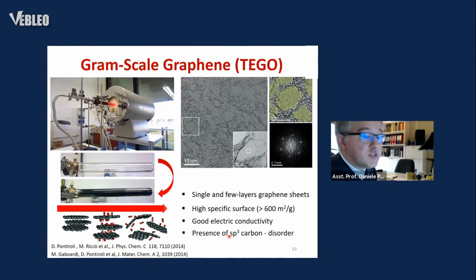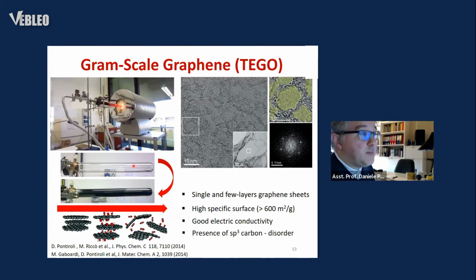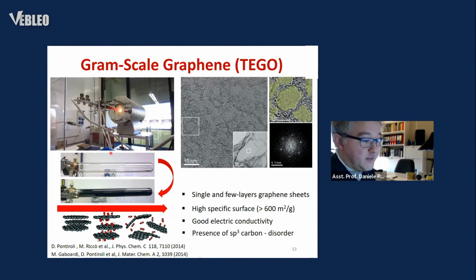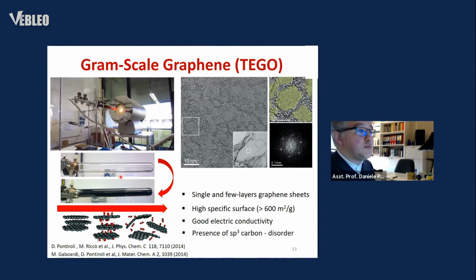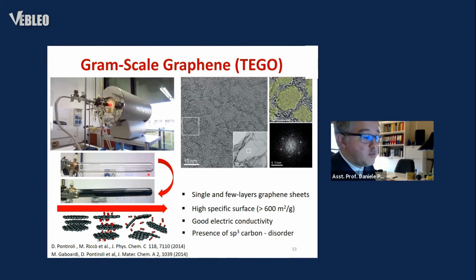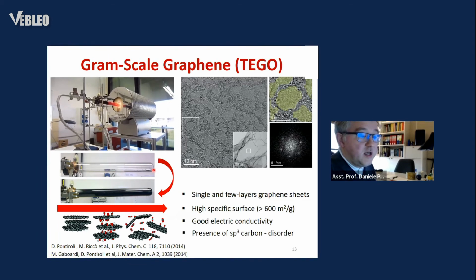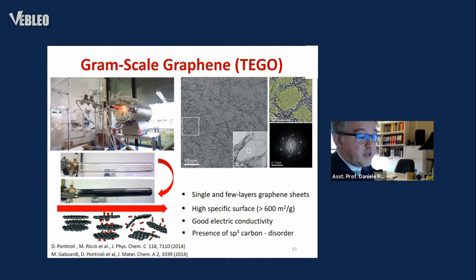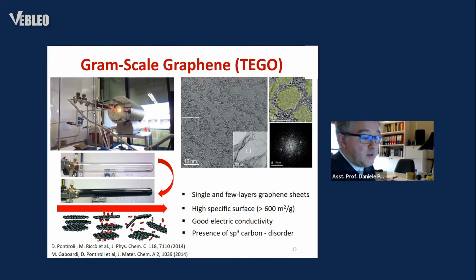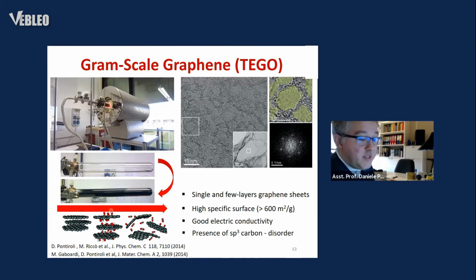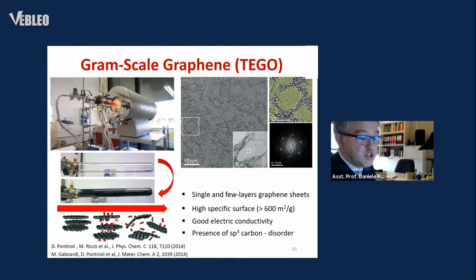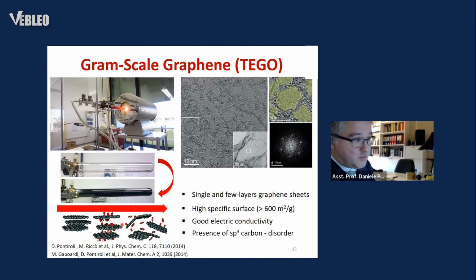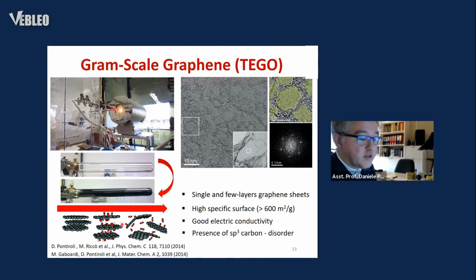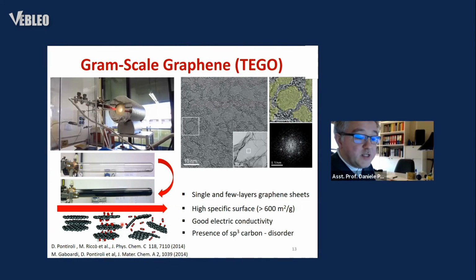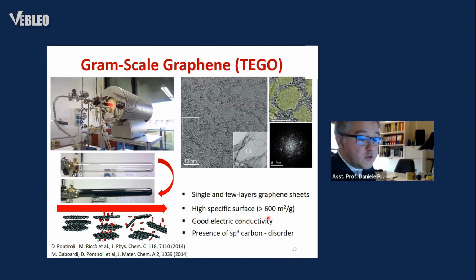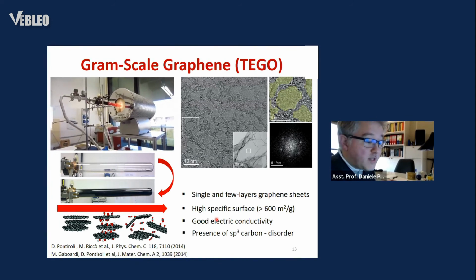In our laboratory, we produce gram-scale quantities of graphene-based materials by means of thermal exfoliation of graphite oxide. In more detail, we start from graphite oxide, obtained by treating graphite with strong acids and oxidants, and we expose it to a thermal shock at very high temperature in a controlled atmosphere. The exfoliation process is promoted by the quick release of the functional groups covalently attached to the graphene sheets. The obtained product contains a large fraction of single and few-layer graphene nanoplatelets, displays a pretty high specific surface area and good electric conductivity, and also quite a large amount of defects.